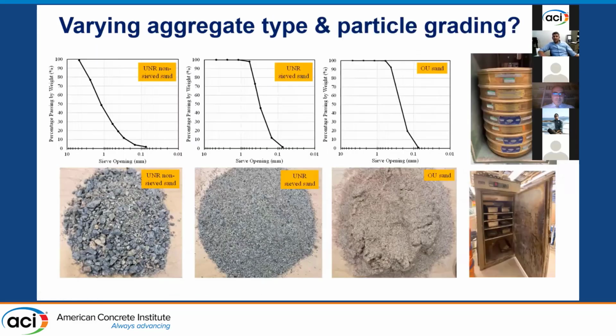The other part is the aggregate type and the particle grading. Again, UHPC, and I have heard this from several presentations today, it's all about the particle packing theory. So we wanted to show, again, on purpose, we are not after a 25 KSI high-end UHPC. We want a practical mix for a specific ABC type of application. So if we are not even going to do sieving for the sand, and you have seen here, these are very large particles, versus a sieved sand that we sourced here in the Nevada part, and then that's the fine sand that we got from Oklahoma, how would these 3 compare.